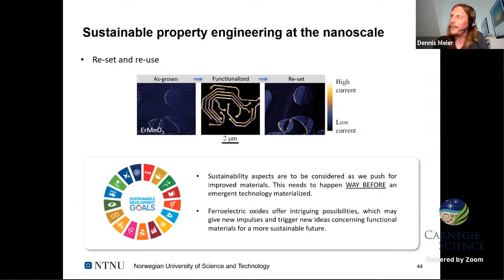So there I cannot say too much about the details. We're investigating that right now, how we can drive them apart and really control where they're sitting, avoid or induce recombination of the defects. From the data we have, we can have them for 2 years if they don't see each other. That is reasonable because there are also energy barriers for recombination. But the very details at this point, it's a proof of concept, so we are still trying to figure out how far we can go with that.